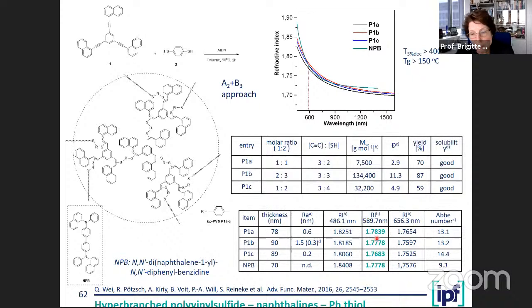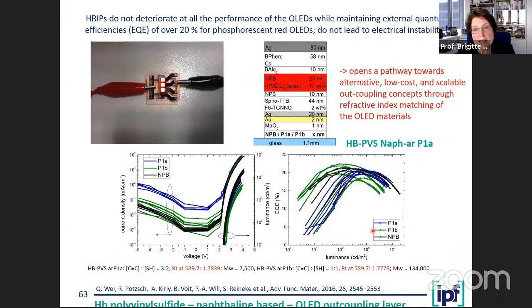And the most important part, I have to say, it's very important that it's branched, because only when it's branched, it's soluble and can be spin cast as thin films and can then be used in such devices to actually have a very new pathway towards a low cost concept to make such devices, because up to now, most of those materials are done by sputtering, so under vacuum of the different layers.